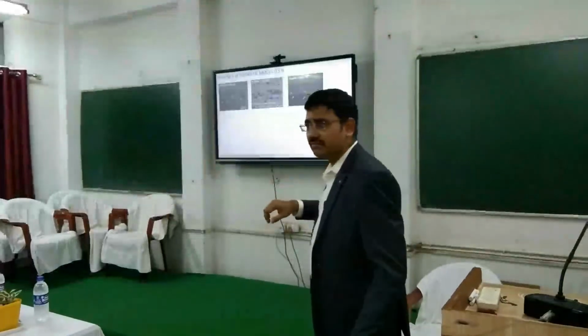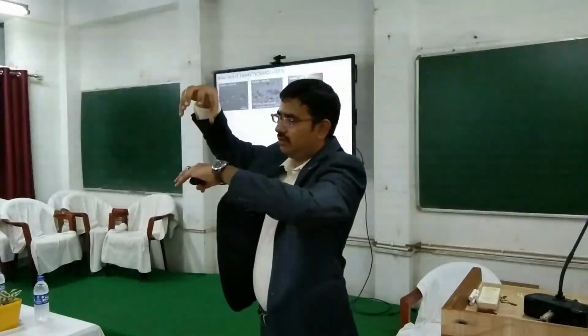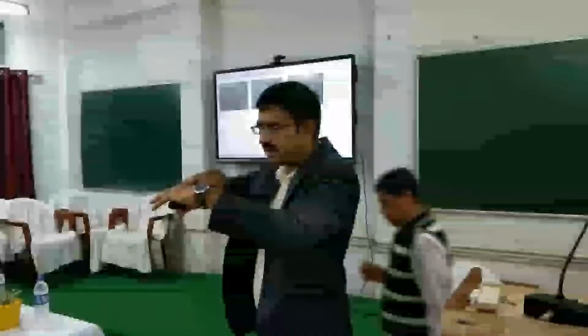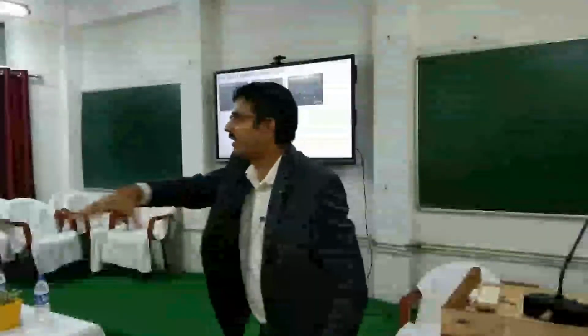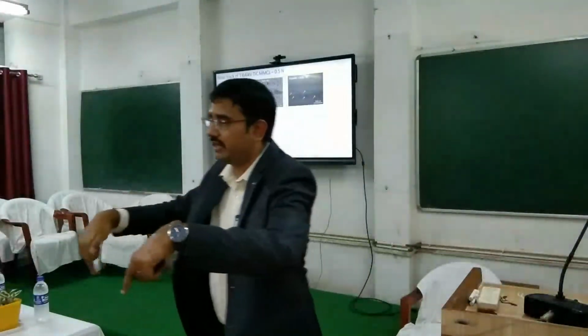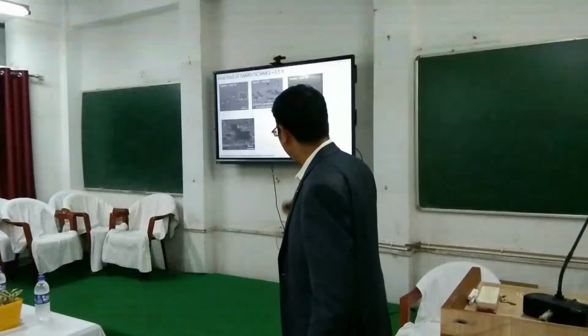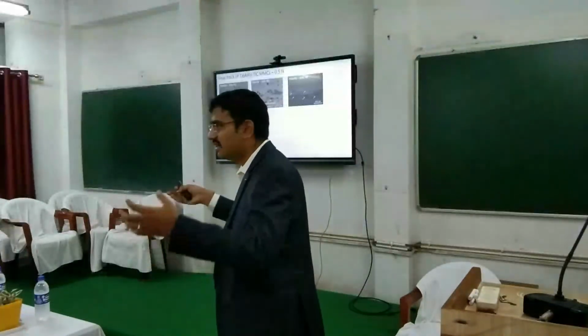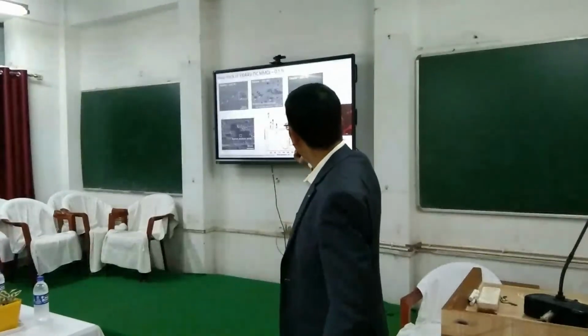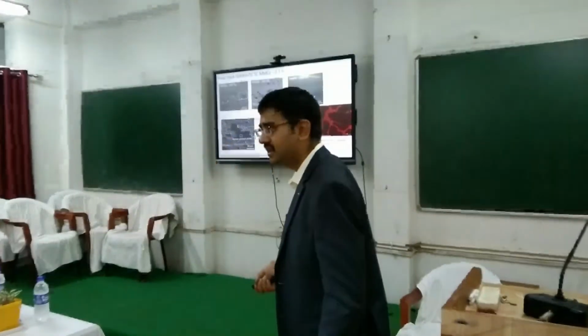Whereas in the case of composite coatings, we saw that protective tribolayers are being formed around the carbide particles. Because the carbide particle is there, the wear debris comes between the ball, which is under load, and the hard carbide particle. So there is a sintering action taking place around these carbide particles due to high load and localized temperature. They are forming a kind of protective layer on the top because of the presence of these carbide particles. Those protective layers are giving load bearing support, and they are preventing the nascent material underneath from getting worn out. That is the tribolayer formation, which is inhibiting the nascent material from being worn out. You can see it is sintering of the wear debris formed in the case of composite coatings. And why it is giving low friction is because you have free carbon in the titanium carbide particles. That is the Raman analysis, and this free carbon is giving an easy shear because of the graphitic carbon, which has a layered structure.